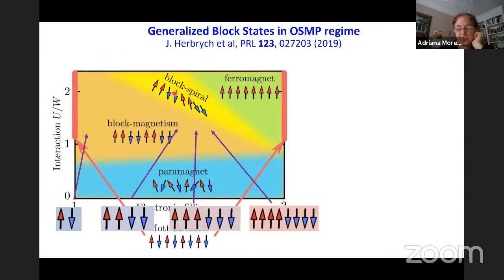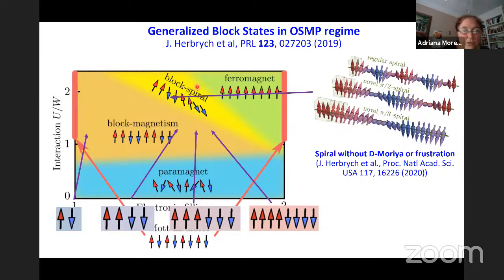This is a block spiral phase, a very intriguing one. Notice that in a regular spiral, spins are tilted with respect to each other. Here we find blocks of 2 spins ferromagnetically aligned that are tilted with respect to each other, and as we increase the doping, we also found regions with blocks of 3 spins tilted with respect to each other.